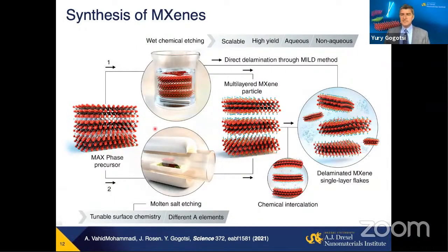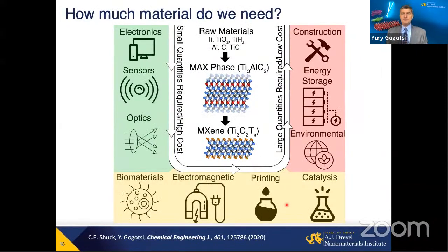Just like we etched in the past, for example, transition metals from carbides to make porous carbon or graphene-like carbons, or as people etched, for example, silicon from silicon carbide to make graphene in vacuum. Same way, we need to chemically remove it here. So this is what brings the surface termination. Typically it's oxygen or OH if etching is done in an aqueous environment; it can be halogens. If etching is done in, for example, molten halide salts, you can get chlorine or bromine on the surface. There are many other methods now that have been reported using halogens in organic solution, gaseous halogens, using electrochemical or hydrothermal etching. But basically, we're looking at a family of materials produced by chemical processing, like graphene oxide.